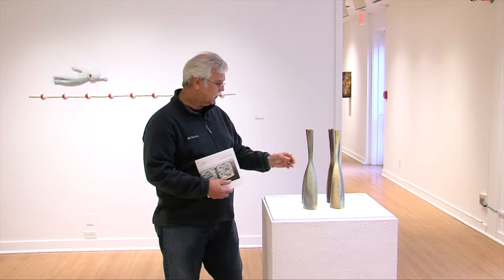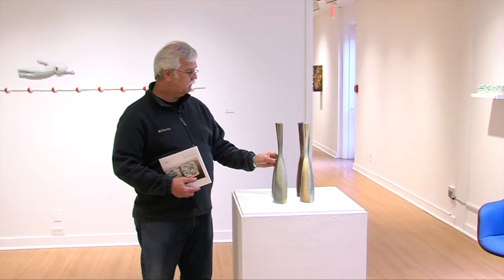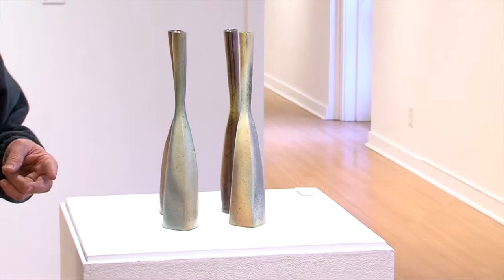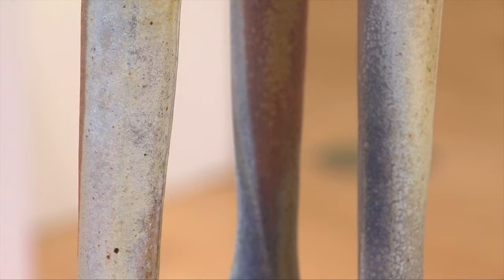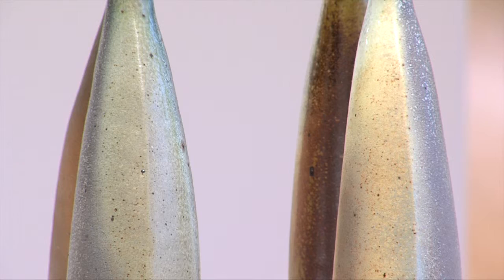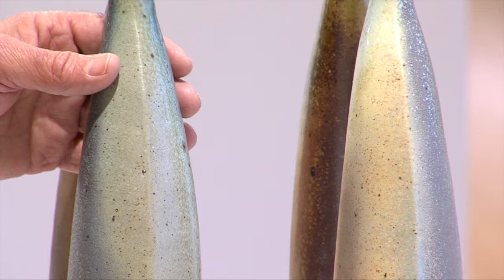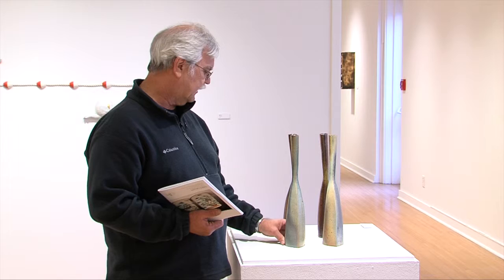I use a salt glaze kiln for firing these things, and my surfaces are arrived at with basically two glazes that I've been using over maybe the past 15 years. There is some added element to what I do with those glazes by spraying some titanium dioxide on the surface before they go in the kiln. There is a change in the response in the kiln, creating a bit more of a matte surface oftentimes, but it also expands the palette considerably, adding in some more of the creamy colors, the tans, and almost white colors that can come in. And so it adds to the variable quality on the surface.